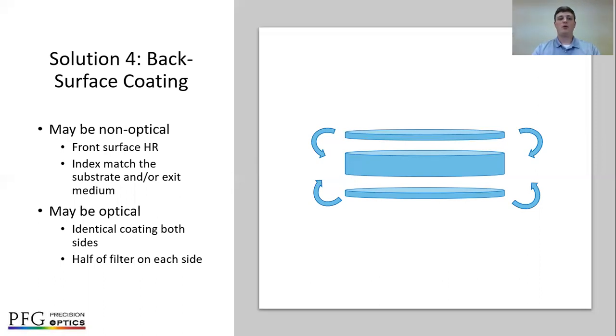If this is a problem, a non-optical stress balancing back surface coating can be designed to achieve this. So this is a coating that's designed to index match either the substrate or the exit medium, which has minimal optical characteristics but provides the counterbalancing stress necessary. And this can be put on an unused back surface on the optic, or it can be put underneath an anti-reflective coating, for example. And so these can provide a counterbalancing stress to maintain flatness. Again, what's necessary is very good characterization of your coating stress so you know exactly how to design this backside coating.